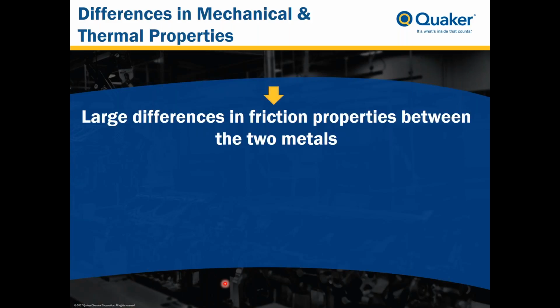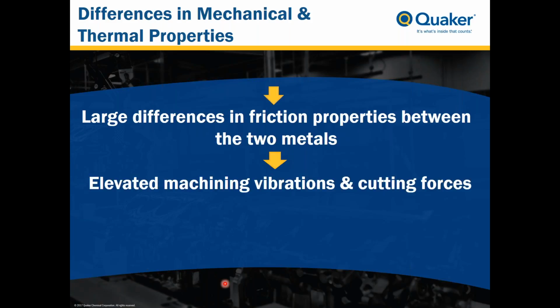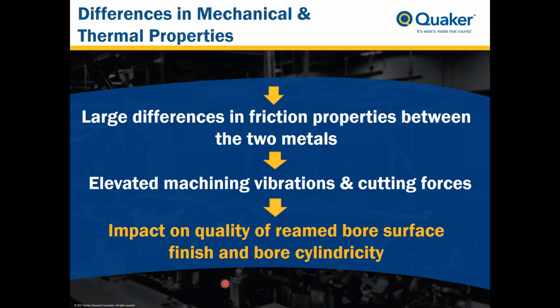To summarize these differences in mechanical and thermal properties, basically the large differences in the friction properties between the two metals that arise because of the differences in the mechanical and thermal properties can lead to very elevated machining vibrations and cutting forces, and ultimately have a negative impact on the real critical specifications of the crank bore during its machining, and that is the surface finish and the cylindricity that's produced. And we'll talk more about that a little later in the webinar.